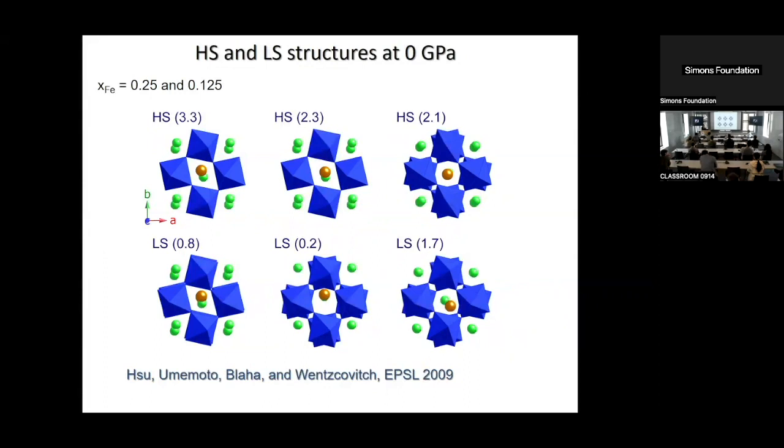First of all, without iron, the gap is about 10 electron volts. With iron, it depends on the configuration. Low spin is approximately 3 electron volts. High spin, it's about 1 electron volt. Intermediate spin, there's more than one configuration, from 0.5 to 2 electron volts. And that's why the title of that paper in Science in 2004 was Non-Convective Layers in the Lower Mantle.